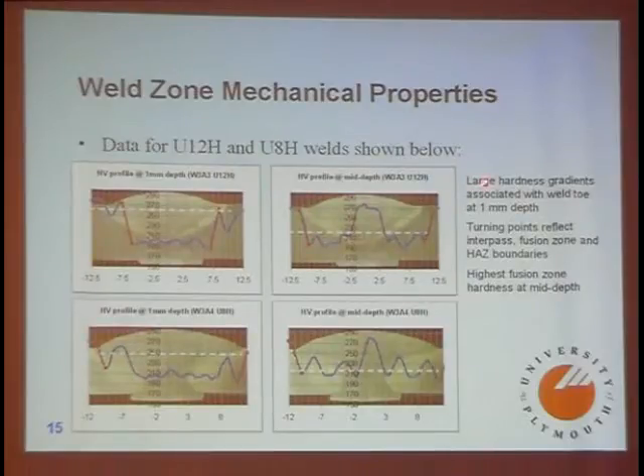So you can say that you do get large gradients with the weld toe. My assumption in this work is that it is the gradients around the weld toe position, because that is where these cracks are going to start, that are the key defining influences on fatigue in some way.